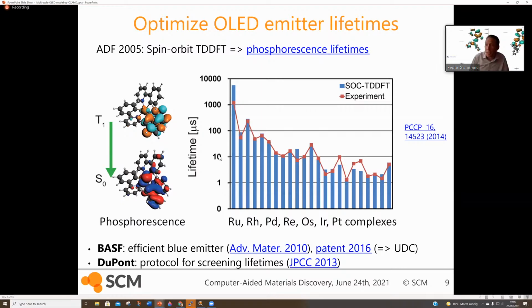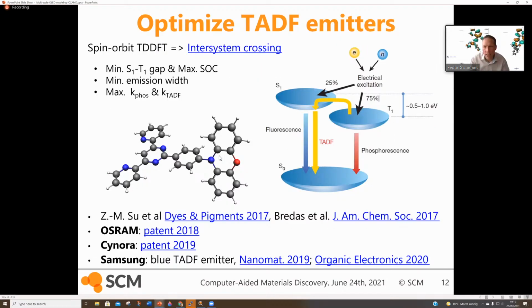For this third generation of emitters, TADF, this spin-orbit coupling is also important, but typically more important is minimizing the gap between the singlet and the triplets, because it's a thermally activated process. The smaller the gap is, the higher the chance that you can reverse inter-system cross from the triplet to the singlet state. And there's also a range of complexes which were initially developed by Cynora, copper-based complexes, which can also phosphoresce. So then you get dual luminescence, so you get delayed fluorescence, regular fluorescence, and you get phosphorescence as well. And so you have three radiative pathways which you can optimize.